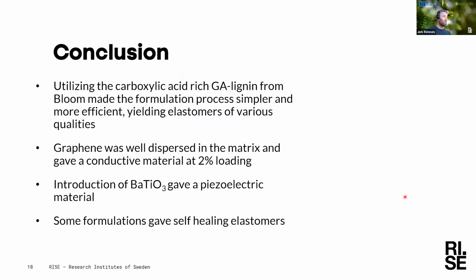But we can conclude that using this carboxylic acid-rich lignin from Bloom made the formulation process simpler and more efficient compared to what we saw in the literature initially, which yielded elastomers of various qualities where we experimented with the formulations. Graphene was also well dispersed in the matrix and gave a conductive material at 2% loading. We could also see that introducing barium titanate gave a piezoelectric material. And in some formulations, we also got a self-healing elastomer material.